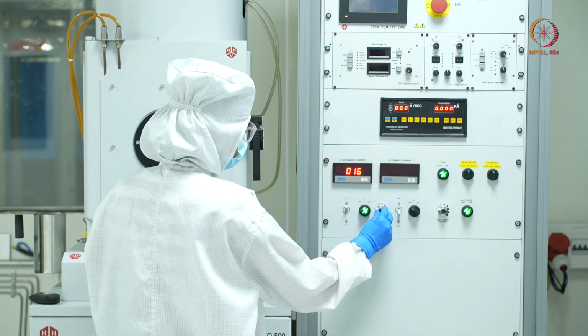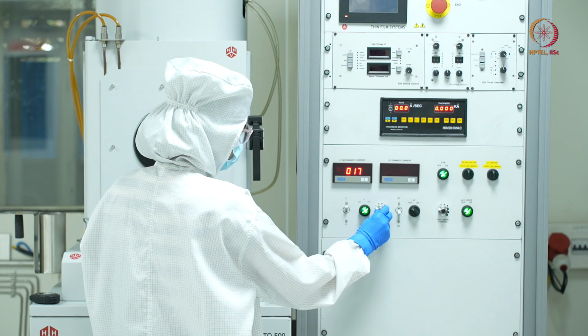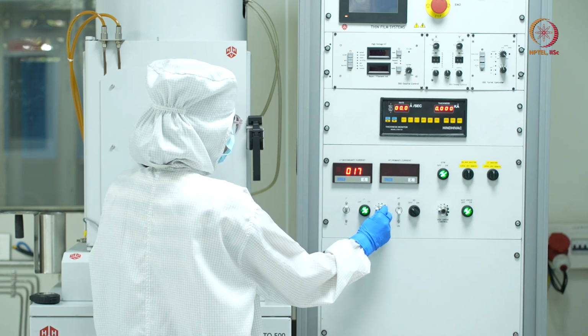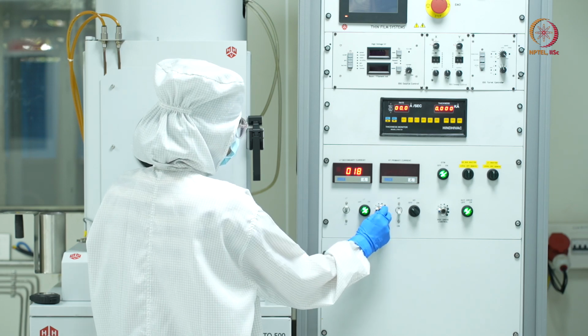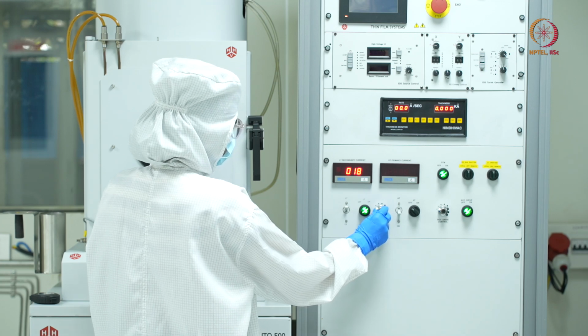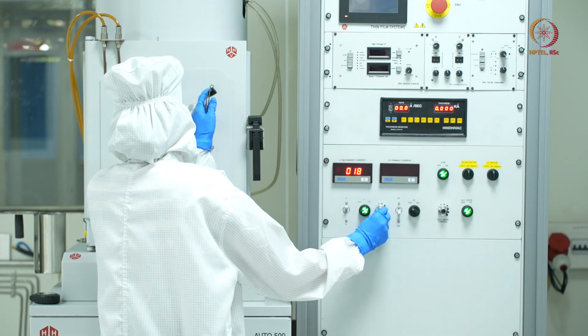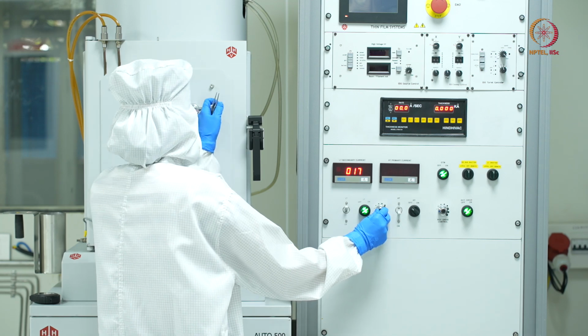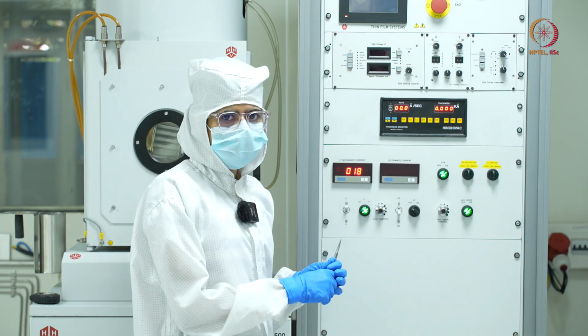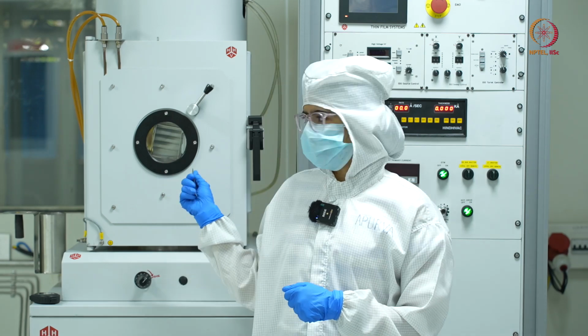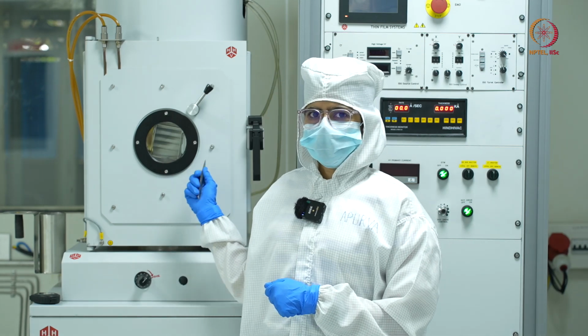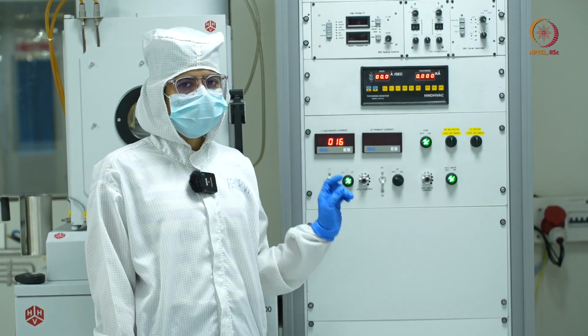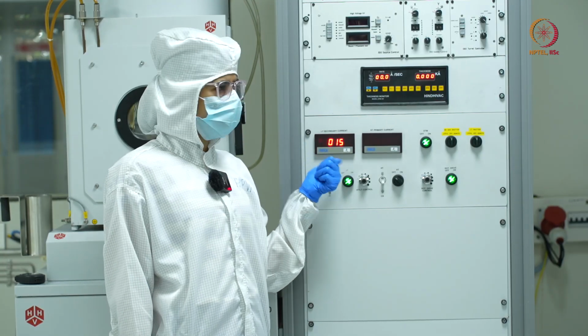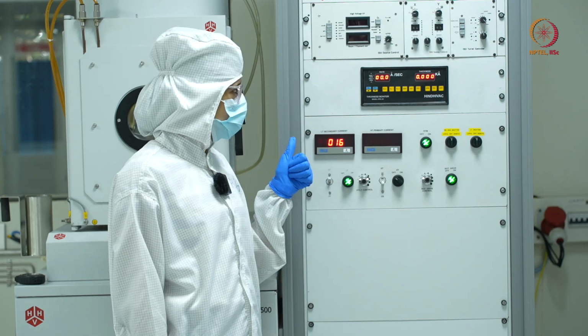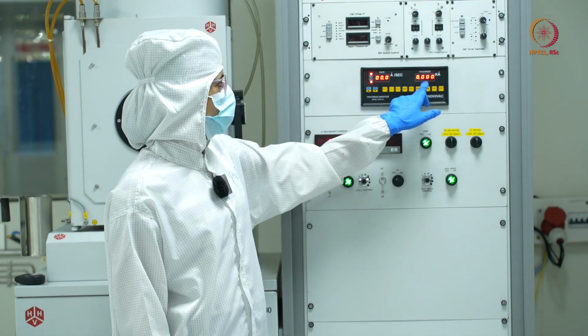I can further go to 17 or 18. I'm just checking from the viewport whether there is a glow on the tungsten basket or not. Yeah, and now we'll have a closer look from the viewport to see the tungsten basket glowing. Now the preheating was carried out for around 1 minute 30 seconds, and now I'll start my DTM so that